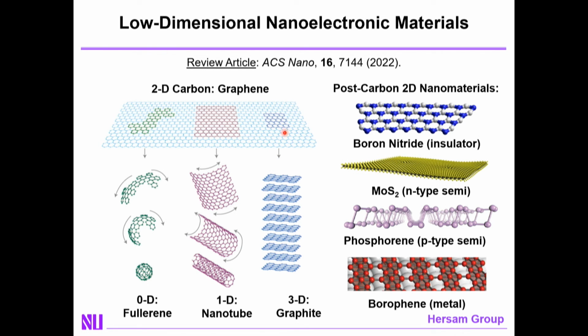Or in principle, you can imagine taking graphene and stacking it up into a 3D lattice. And if you did that in an ordered manner, you would get to graphite. In practice, though, you rarely go from graphene to graphite, but rather the other way, starting with graphite and then peeling away down to the atomically thin limit. This process, once you learn how to do it for graphene, can be applied to other van der Waals solids, such as hexagonal boron nitride, which is electrically insulating, molybdenum disulfide, which is a relatively wide bandgap, typically N-type doped semiconductor, phosphorene, which is the phosphorus analog of graphene derived from black phosphorus, narrower bandgap semiconductor, typically P-type doped.